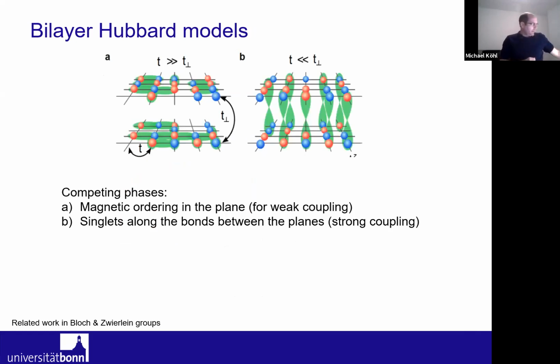Okay, so this brings me now to the second part of the talk that I would like to discuss with you, and that is about the bilayer Hubbard models. So far I've been talking about a single two-dimensional layer with spin 1/2 particles on the lattice in there. So this standard two-dimensional Hubbard model. And we are now interested to see what happens when we actually allow coupling between adjacent planes. So to this end, we implemented an additional superlattice in the vertical direction, which allows us to couple always pairs of these layers to one another with an adjustable coupling strength.